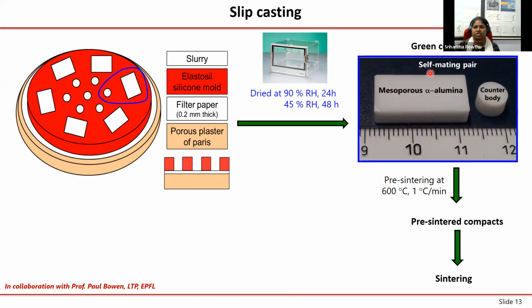So this is our self-mating pair for our tribological test. The bottom specimen looks more like a cuboid, and the top specimen looks more like a cylinder, and we are going to end up having a flat on flat configuration. For these green compacts, if you remember, there was polyacrylic acid, octanol, and ammonium hydroxide, things like that. At least we have to get rid of all the organic materials present in the sample.